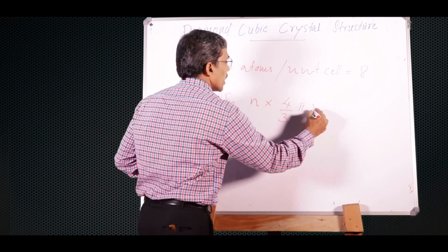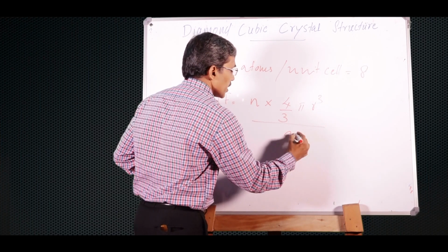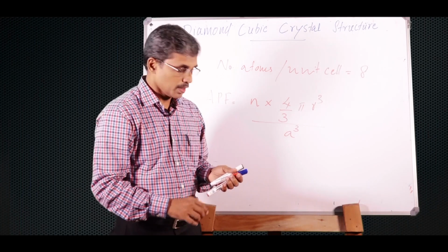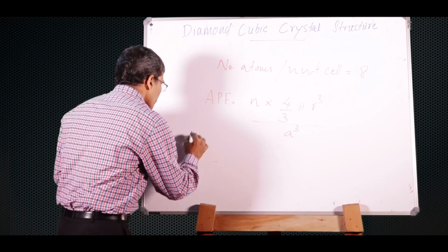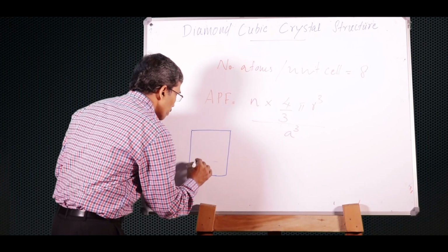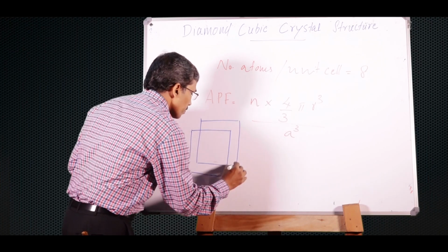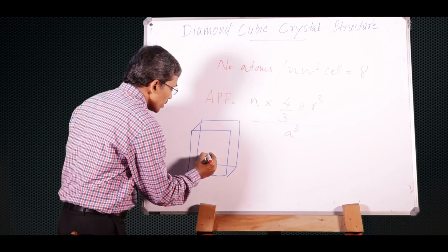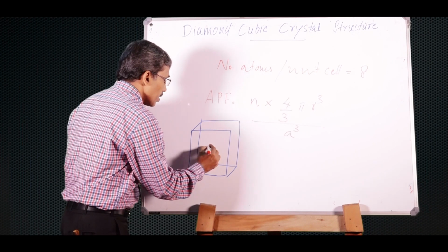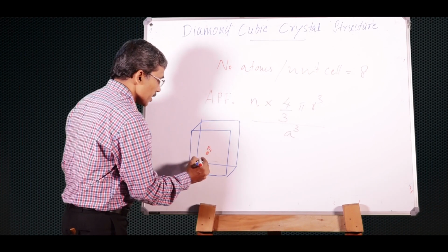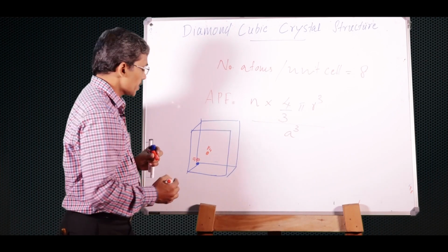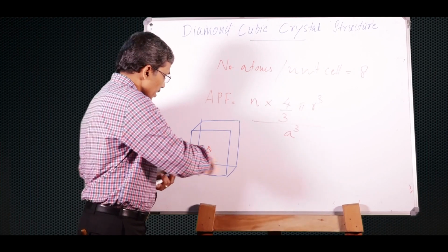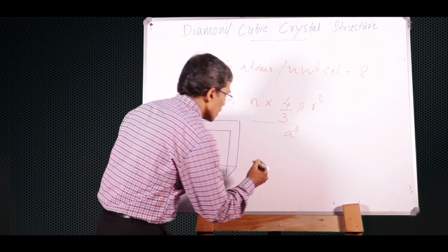volume of the atom, that is 4/3 pi r cube, divided by volume of the unit cell, that is a cube. So we want this radius of the atom. So here one atom is at, we have seen, when we take this cube, one atom is at 000 position and one atom inside, that is centroid of the tetrahedron, that is at 1/4 position. So 000 position and 1/4 position. So if you want to find this distance